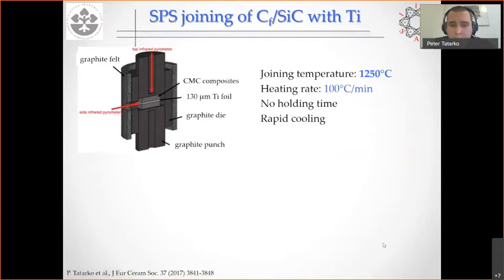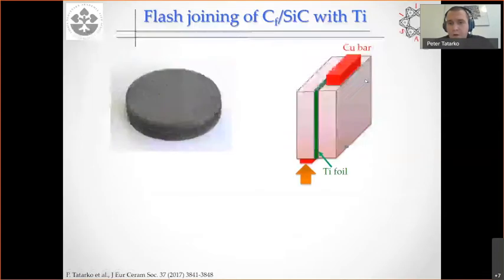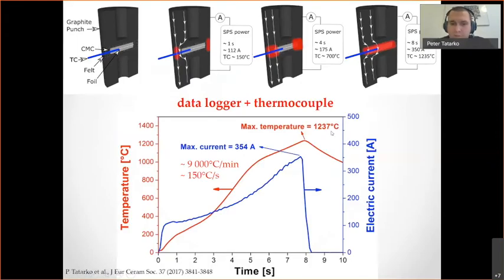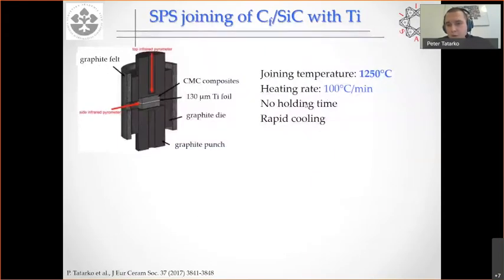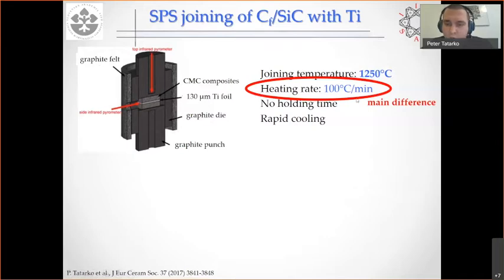So the very last part is, of course, the comparison with the standard SPS joining, because we set up a new process here, we didn't use the graphite die, we were playing with the heating power for an extremely short period. So we wanted to compare with the standard SPS process. We did the same thing, but this time we used the graphite die again. And you can see we used the same temperature as we measured here. You remember here it was about 1250. We used no holding time, as it was not a flash process, and we also used rapid cooling as for the flash process. The only difference was the heating rate, of course, because here it is 100 degrees C a minute, which is the standard heating rate for the standard SPS process.